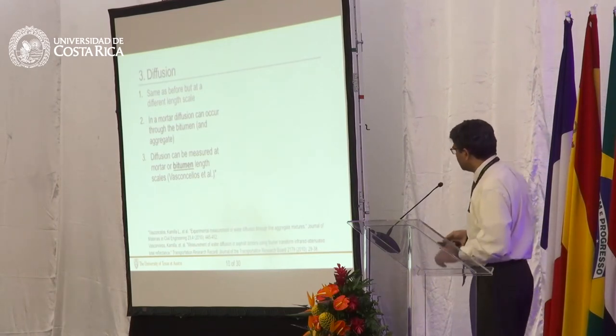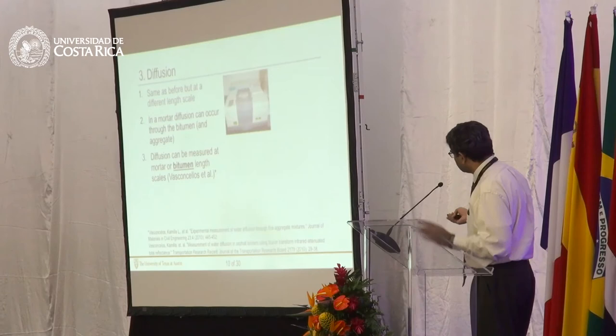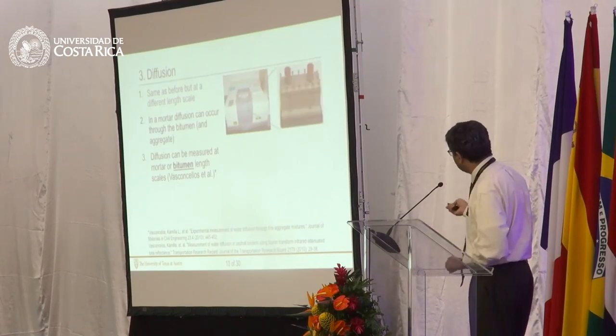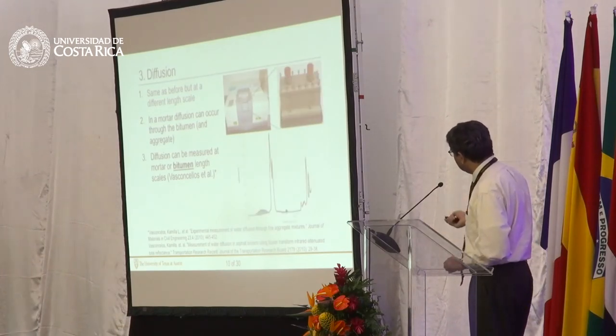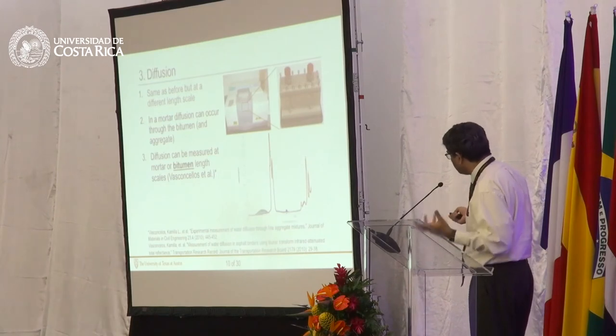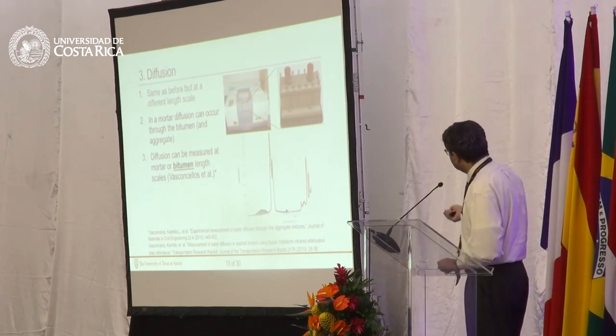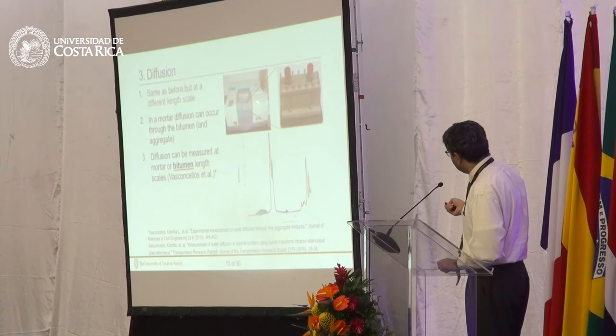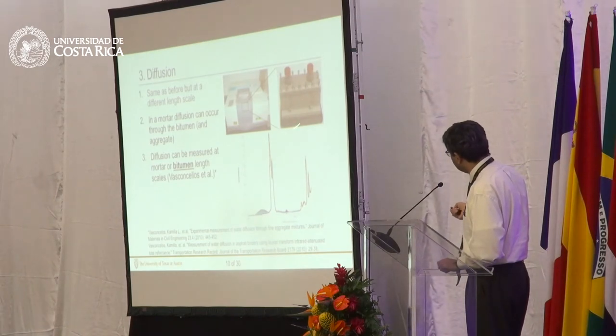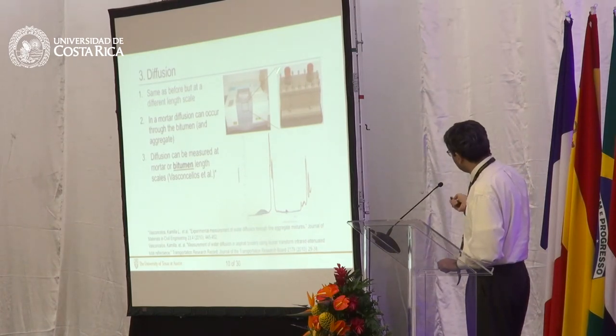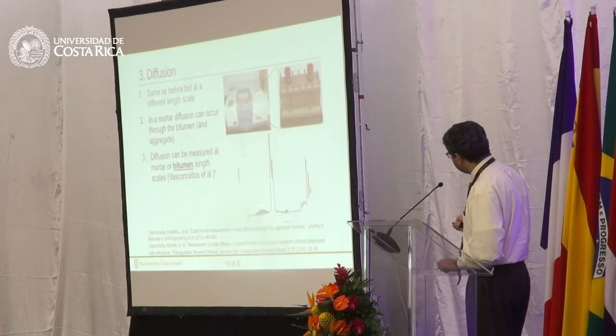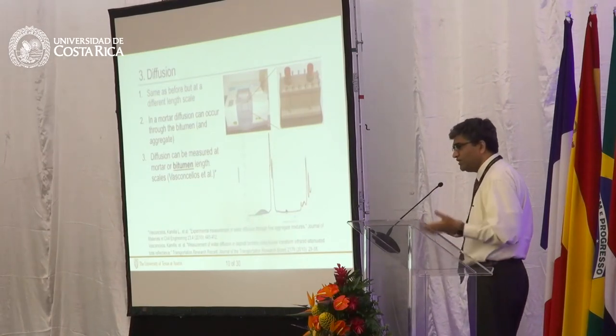Most of the time, it's traveling through bitumen, and there is another study by Dr. Vasconcelos that used an FTIR to measure the moisture transport and diffusivity of water through the bitumen. In this case, she used an FTIR device with a little chamber that fit into the device to control the humidity or water content in there. And this peak that you see here is actually a peak for the water.